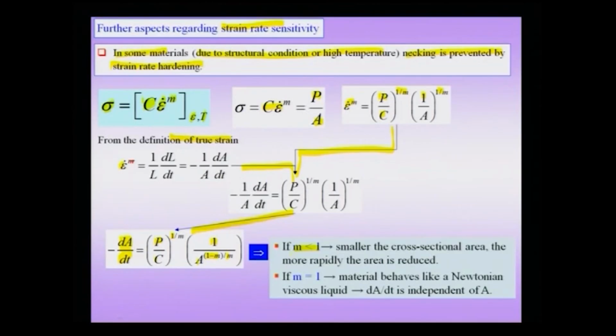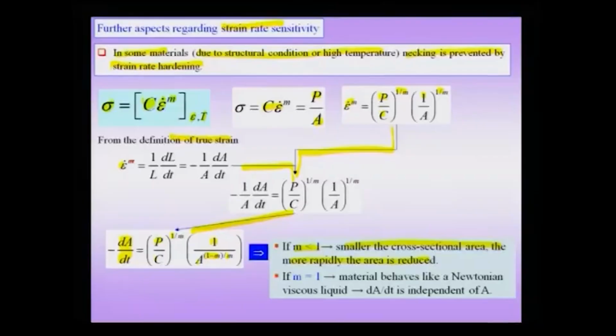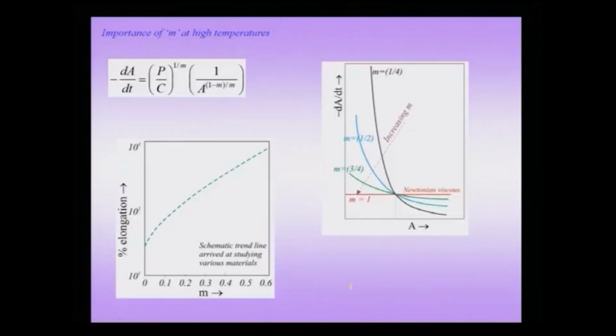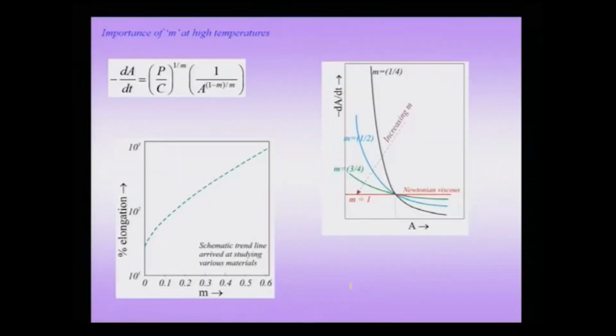If m is small, the smaller the cross sectional area, the more rapidly the area is reduced. That means, if I have a small strain rate sensitivity, then the smaller cross sectional areas will decrease even more rapidly, and that is not a good condition for obtaining long elongations. Of course, if m equals 1, it becomes like a Newtonian viscous liquid, but between small m and large m, we will try to understand how this relationship can be understood better using plots.